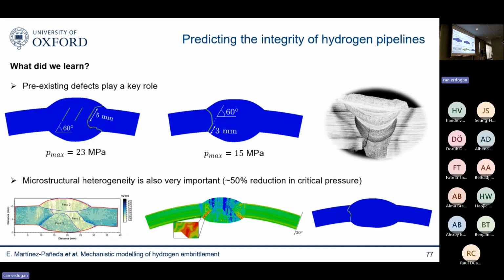And I don't have time to go through the details, but we learned a number of things. What we learned is, first of all, that defects matter significantly. As you expect, residual stresses also matter significantly, and microstructural heterogeneity matters. This is something that wasn't 100% clear, but it seems to be clear. And what we found quite interesting is that when you have a critical defect of 3 millimeters along a hard heat-affected zone, which is something that we have seen on natural gas pipelines taken out of service, your failure pressure could be as low as 15 megapascals. And this is problematic because 15 megapascals is one of the numbers that are being discussed in the industry to transport hydrogen.